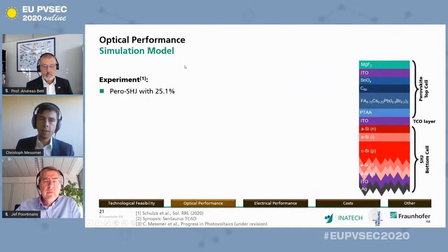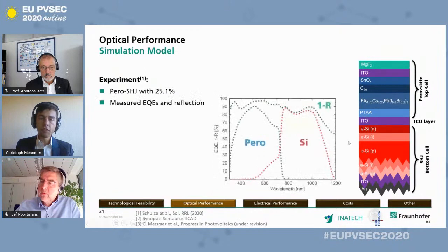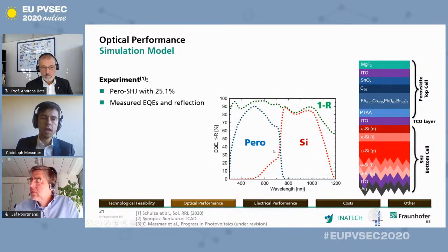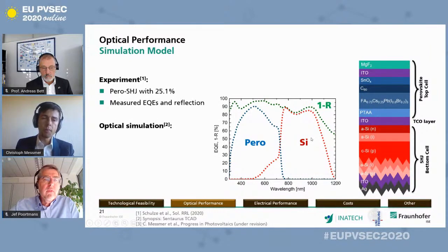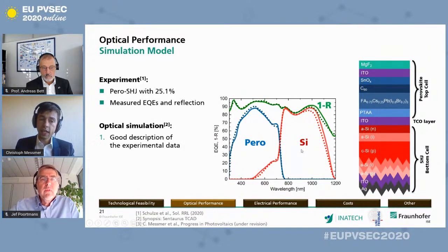So we had a simulation model based on our experiments. Here you can see the perovskite silicon heterojunction, which is presented by Patricia this afternoon. And for this, we measured the external quantum efficiencies and reflection, and then compared it to our optical simulation. And we gained a very good description of the experimental data of this whole layer stack. And for details, I want to refer to a paper which is currently under revision, shown here at the bottom.